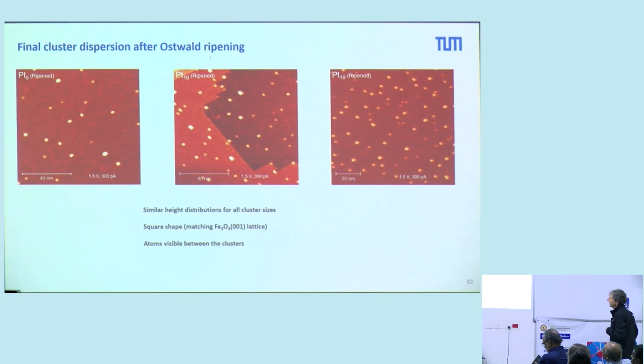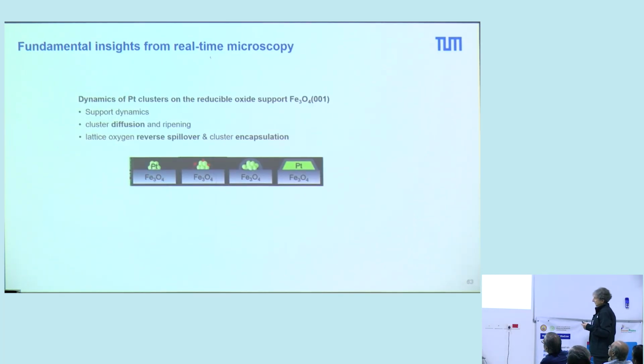Yeah. Okay, that means we have a dynamic system, and if you heat up, then we form stable clusters, square shapes, platinum 5, platinum 10, platinum 19. We start with, of course, the number of atoms of 5 are 4 times lower than platinum 19, and you also see a lower density. That means at one point you make stable structures, which may be inert or chemically reactive. I hope I could convince you that these clusters are dynamic, that we can have different processes. On iron oxide, we have these processes I described to you, but this is unique for iron oxide. If, for instance, on ceria, we have another dynamics. Here, we don't have this encapsulation, but we have a flattening of the cluster as a function of temperature. So we have to somehow really study the system as a whole. It can vary.